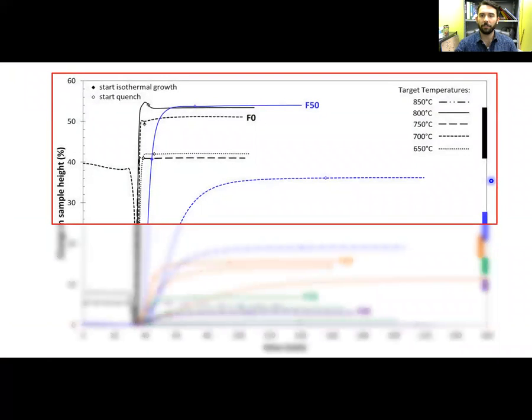If we move to the upper portion of the inflation diagram, you'll notice F50, the 50% crystalline samples, far exceeded anticipated values by up to 26%, and in one case nearly overcame the crystal-free analog. Prior studies have stated, at least for crystal fractions less than 0.4, that the presence of crystals impedes isolated spherical bubble growth and promotes distortion. This in turn facilitates bubble coalescence and earlier outgassing. Coalescence, however, requires ease of ductile flow within the surrounding melt to occur.